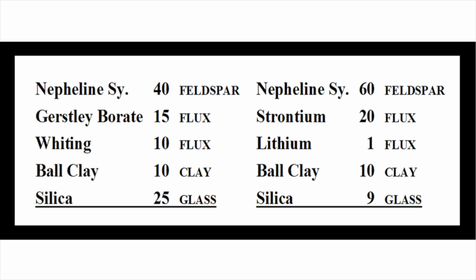You may recognize one of these. The bulk of the glaze content, again, is the feldspar. Secondly, the flux strontium promotes a matte surface, whereas Gerstly borate in the other glaze is a strong, low-melting, glossy flux. Thirdly, one of the glazes has a very high silica content. The glaze on the left is a glossy glaze, and the glaze on the right is a matte glaze.